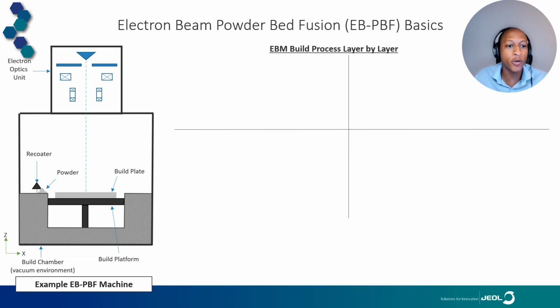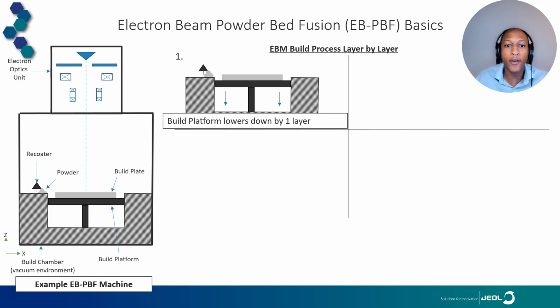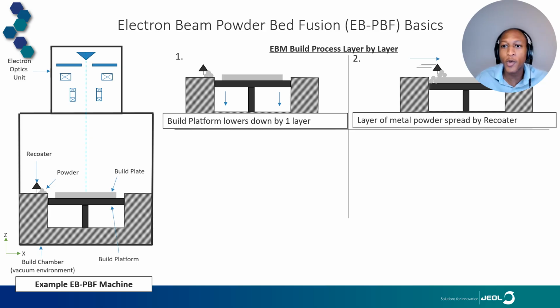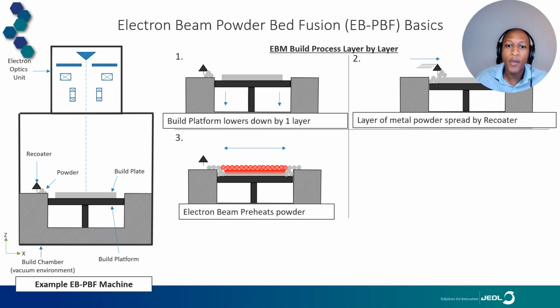We have a recoater, which spreads powder across the build plate, and we have a build platform that moves down based on the layer thickness that was selected. Layer by layer, between layers, the build platform lowers down by a layer. The layer of metal powder is spread by that recoater, and then from there, we turn on our electron beam. In our initial process, the electron beam preheats that powder, and what we call sinters that powder, by having a defocused electron beam scan across that powder bed.